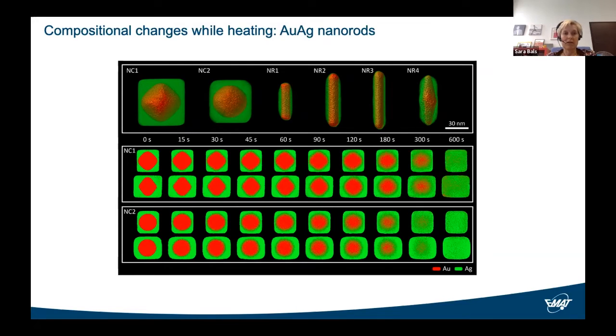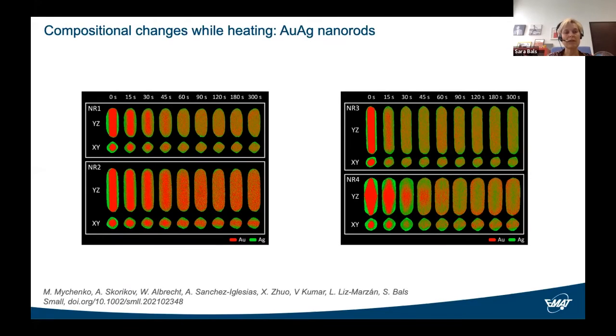So if we now compare both nanocubes and we made comparison along different crystallographic directions, again, we see that the alloying performs in more or less the same way. So that enables us to conclude that the role of the interfacial facets is not dominant. So next we are comparing the 2 single crystalline nanorods. Again, we see a similar trend, and we conclude that for the sizes in this range, the size does not play a dominant effect. However, if we now compare the single crystalline nanorods to the pentatwinned nanorods, we see that the pentatwinned nanorods start alloying significantly faster.